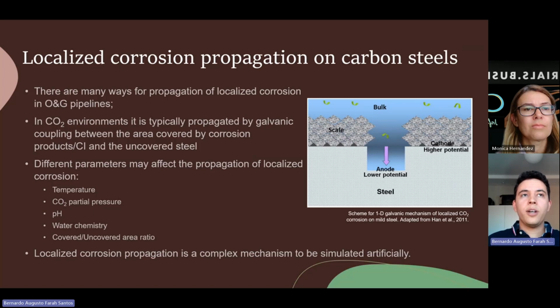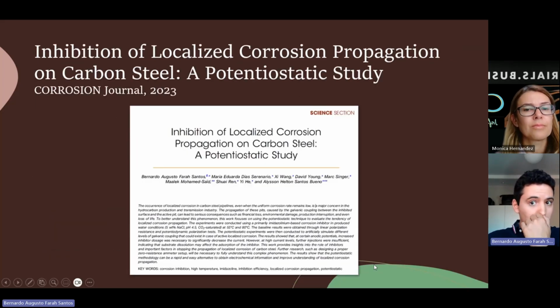Since we have a difference in potential, a shift in potential between the area that is your pit, your localized corrosion, and the surrounding areas covered with corrosion products or inhibitors, there is a technique that can simulate this shift in potential that will consequently lead to a current flowing. That is the potentiostatic technique. And that was what we did in this first stage of my PhD, simulating propagation of localized corrosion using the potentiostatic technique.